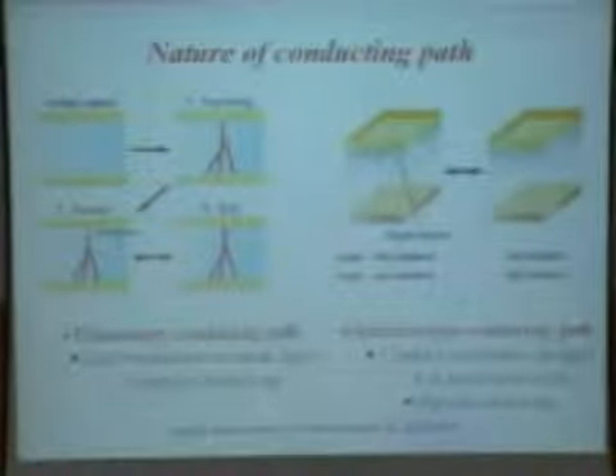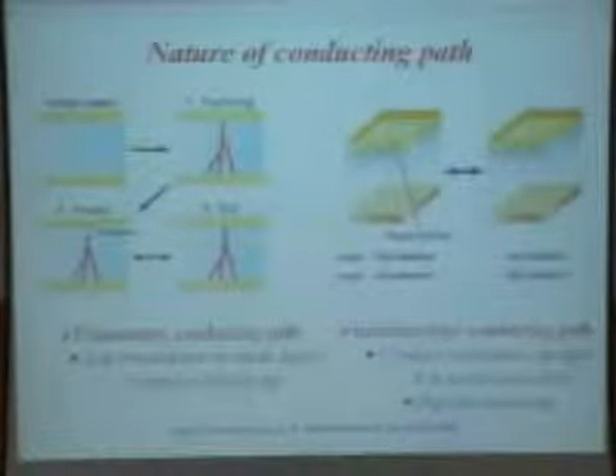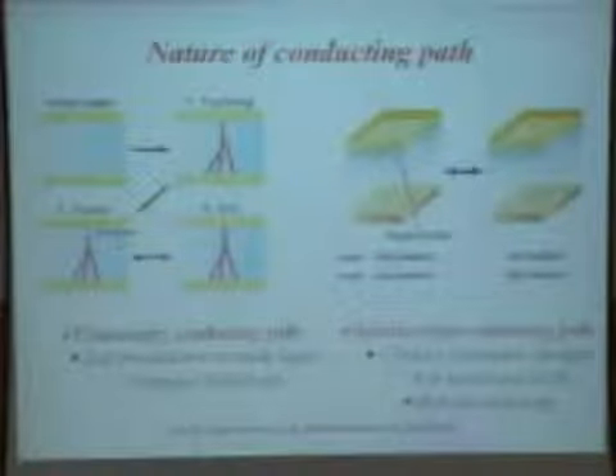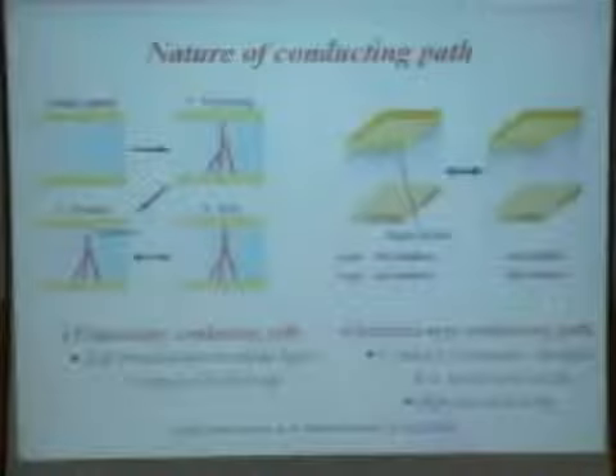You again apply voltage so that forming again takes place, but now because the filament is already there, you don't have to go to those high forming voltages. You can work with a smaller voltage. That is called the set voltage. So this is one sort of mechanism. There are other mechanisms also, and in different materials there are different types of mechanisms.